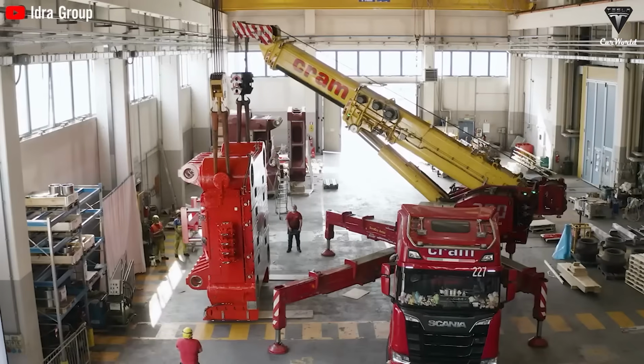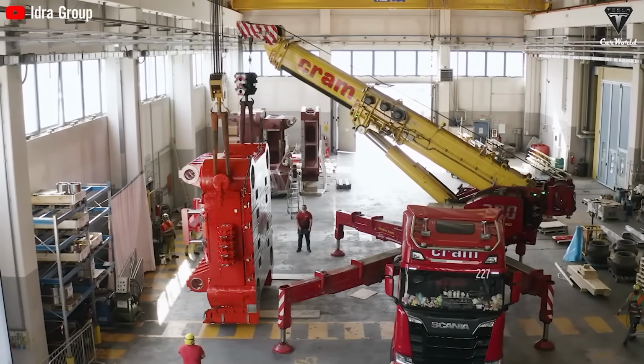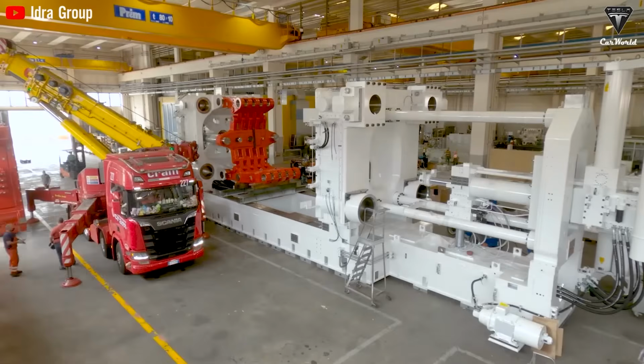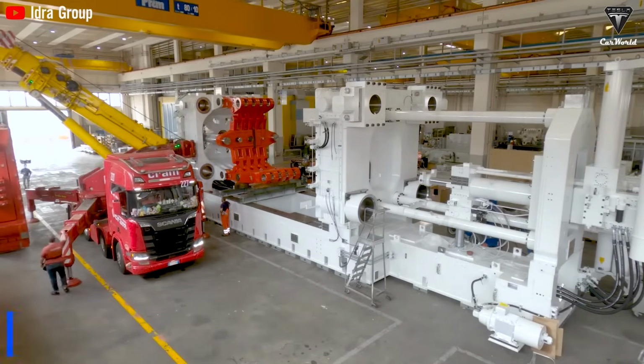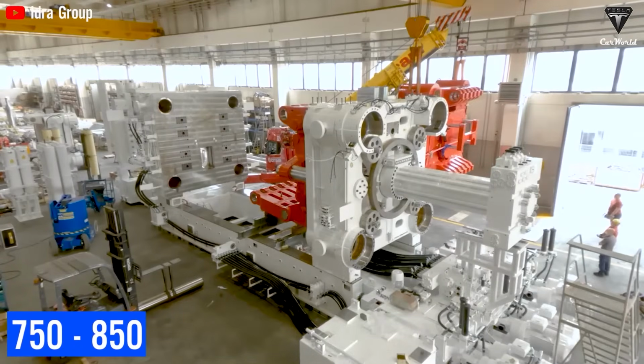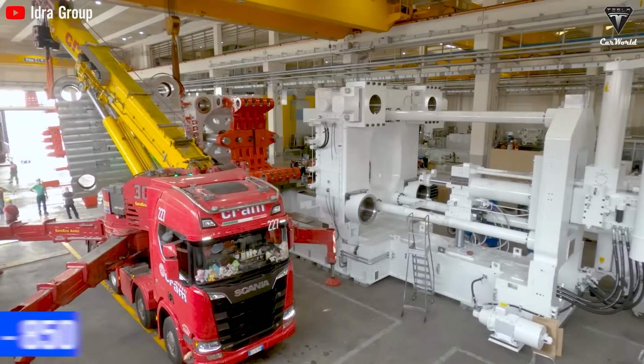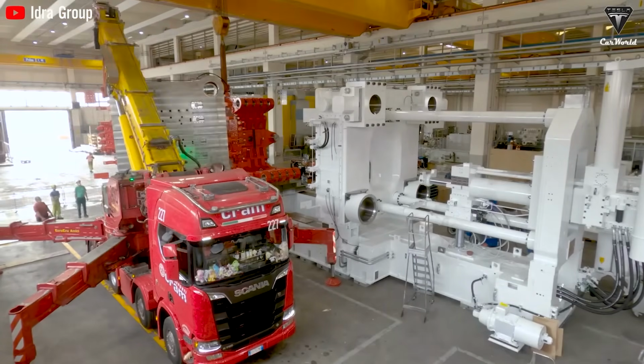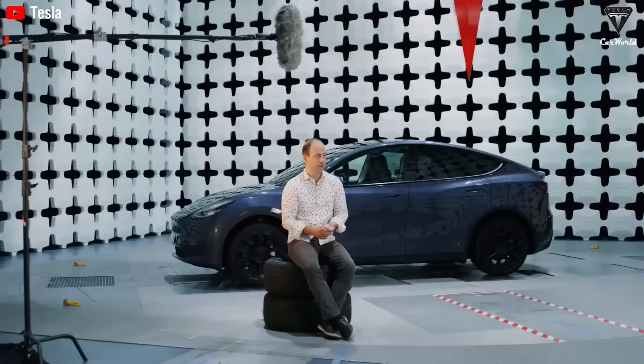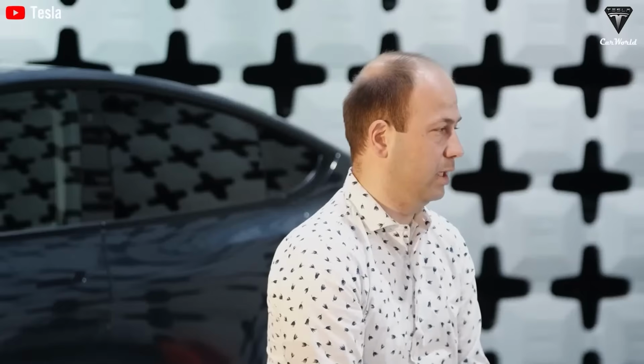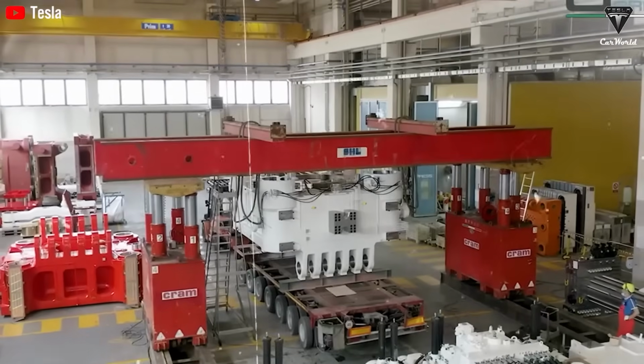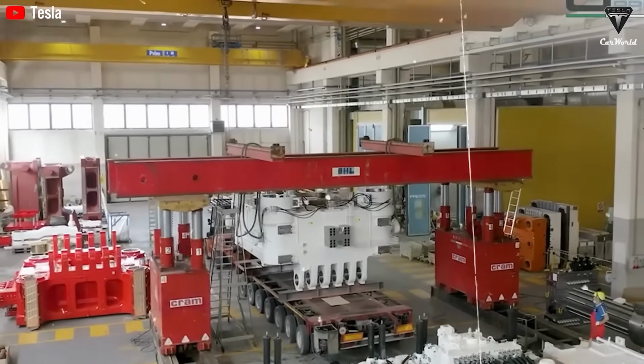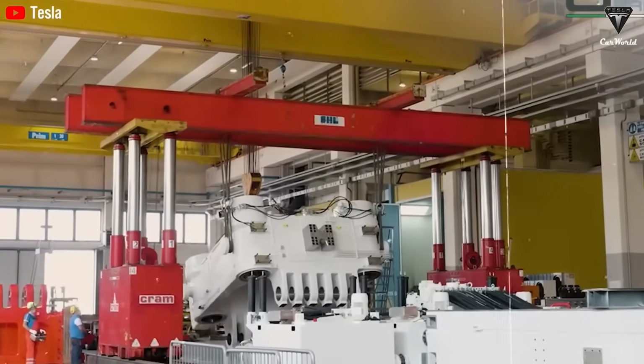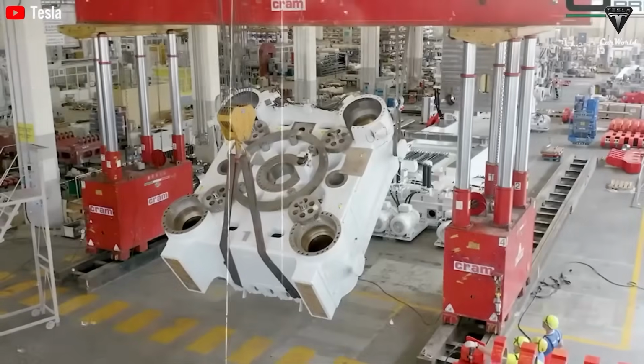Aluminum ingots are melted in a gas-fired furnace at roughly 850 degrees Celsius, held in an electrically heated chamber at 750 to 850 degrees Celsius, filtered through nitrogen and argon to remove oxides and particles, injected at high speed into a lubricated steel mold, solidified, cooled, trimmed, X-rayed, and recycled. What distinguishes the new machine is scale.